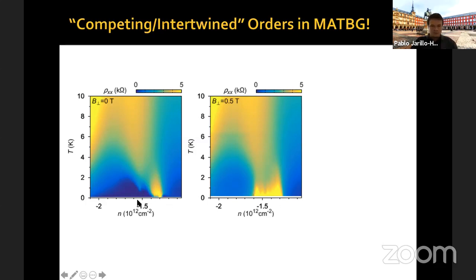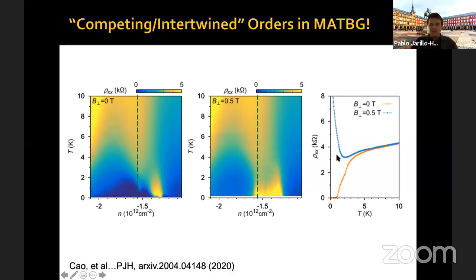But this wedge in particular leads to a strongly insulating region here. If you take a vertical trace here, so that you don't see only color plots, at the exact same doping and at zero and finite magnetic field, you can see that at zero magnetic field the system becomes superconducting. At finite magnetic field, there is a metal to insulator transition at a certain temperature.